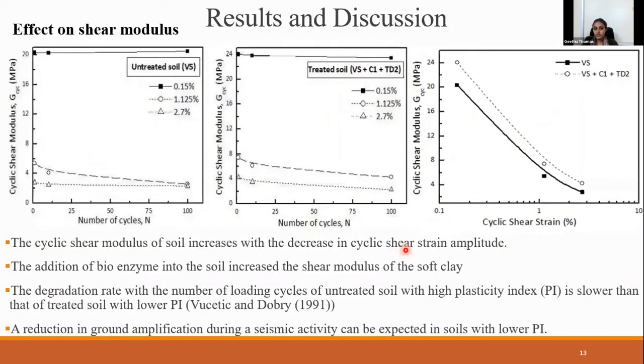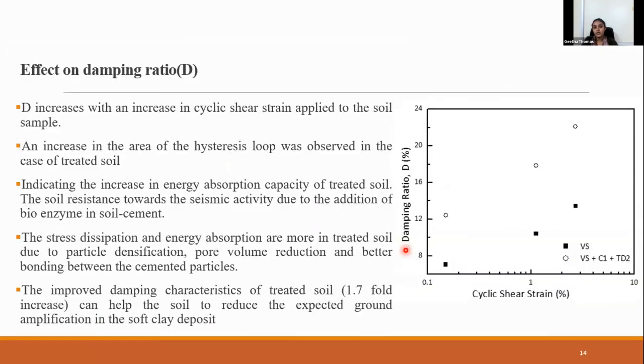The treatment effect on shear modulus is illustrated in this graph. You can see that the shear modulus increased significantly in the presence of 1% cement and TerraZyme, and also the degradation rate of shear modulus is lower in the case of treated soil. That means a better seismic response is expected in the treated soil. And also the damping ratio increased 1.7 times that of untreated soil.